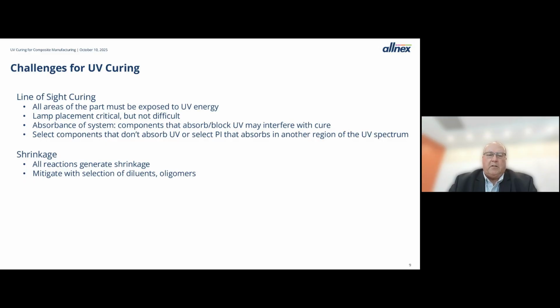You do have to be cognizant of the absorbance of the system. Components that absorb UV energy can compete with photoinitiators and possibly interfere with cure. There's ways around that, and we'll talk about that later. There's also shrinkage. Everything shrinks. Anything that reacts is going to have shrinkage associated with it. That's well known with just about any system, and in UV systems, you can mitigate that through your selection of diluents and oligomers. So some challenges for UV, more things that you need to be aware of, not necessarily things that are going to prevent you from using UV.